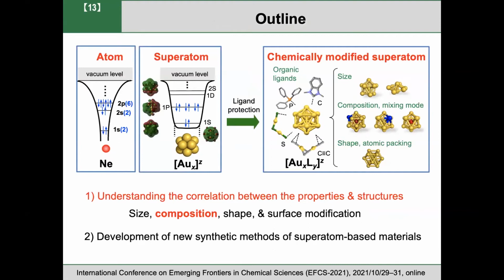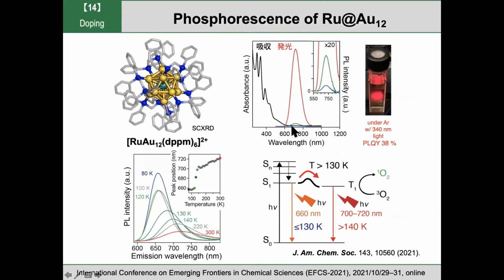Here is one example. We can synthesize ruthenium-doped gold clusters. The surface is phosphine ligands, but you can ignore this outer layer. You can focus on this core. The core is made of ruthenium-centered gold-12 icosahedral packing. This cluster has this kind of optical absorption spectrum and exhibits intense photoluminescence, red light emission. The quantum yield is nearly 40%. This is a quite large number. So these clusters can emit light with high efficiency.